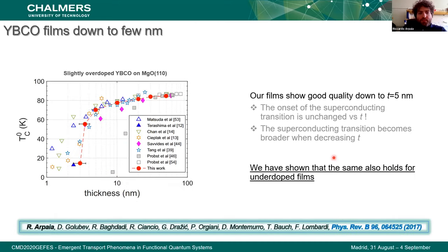Then we have done ultra-thin films, and also in this case, our films show very good quality down to 5 nanometers. What does it mean? This means that the onset of the superconducting transition is unchanged, because this is set by the oxygen doping level of the film. And so it's always the same as a function of thickness. Vice versa, the superconducting transition becomes broader and broader when decreasing the thickness because the film approaches a 2D material. So the transition is ruled by the Berezinskii-Kosterlitz-Thouless transition, and the zero resistance critical temperature becomes smaller and smaller.